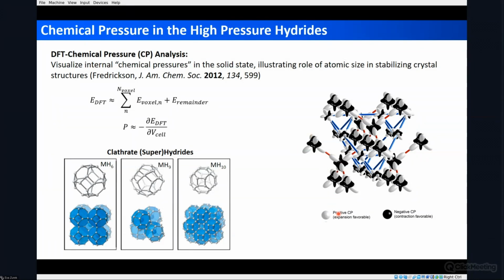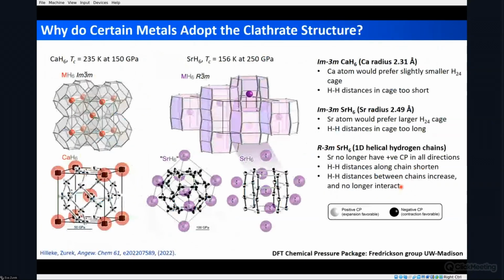And what this type of method shows you is if you have this kind of a positive chemical pressure, it tells you that the lattice would like to expand along that direction. And if you have a negative chemical pressure, these black lobes, then it would like to contract around that position. So we wanted to take a look at why in some of the high pressure hydrides you get the stabilization of these three-dimensional lattices with high TCs, and in other hydrides, CaH6 and SrH6, on the other hand, you get what is known as a Peierls distortion.